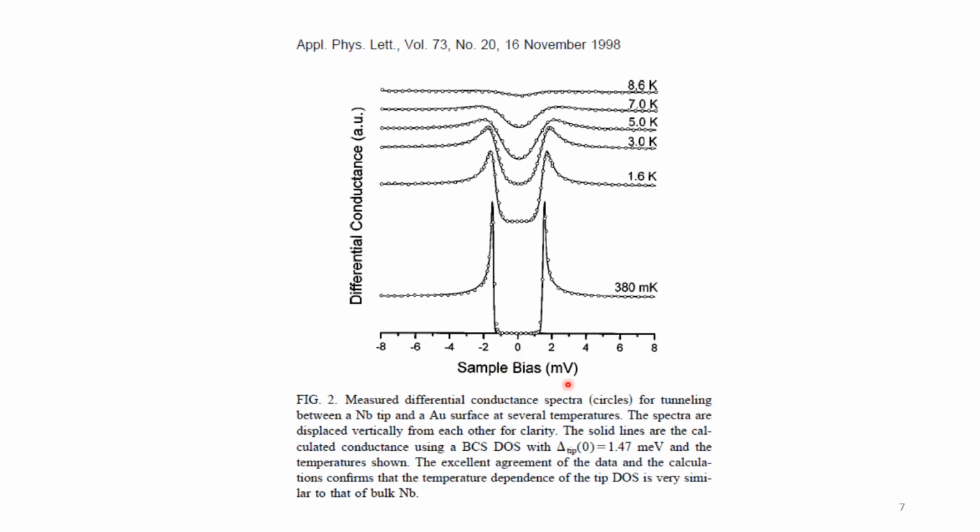And you see exactly at 0, that is where the Fermi level lies, there is hardly any, so 380 millikelvin is when the system is perfectly a superconductor. Okay, so you see that there is no carrier density at all for a sizable portion around the Fermi level. So at these energies there is no carrier, and then suddenly, as you go slightly away, at these energies there is a sudden discontinuous change, and then again the thing happily behaves as a metal.